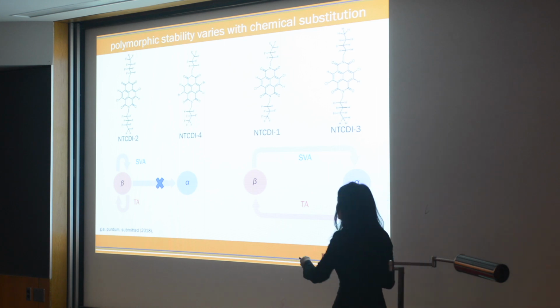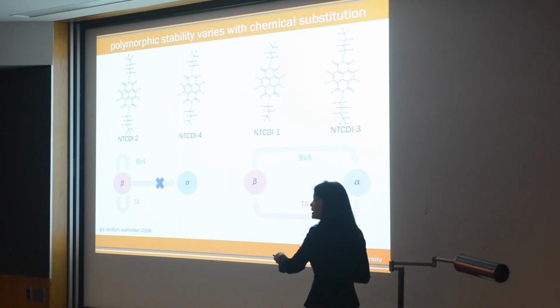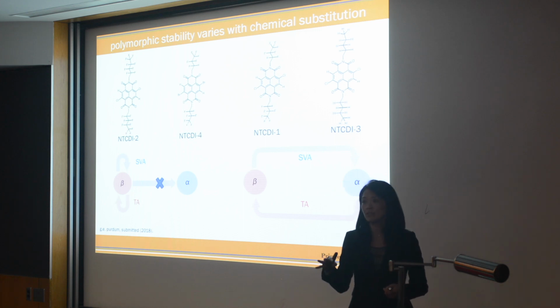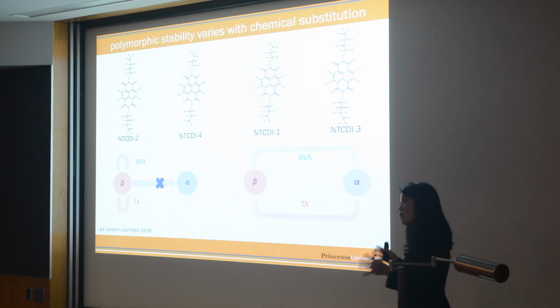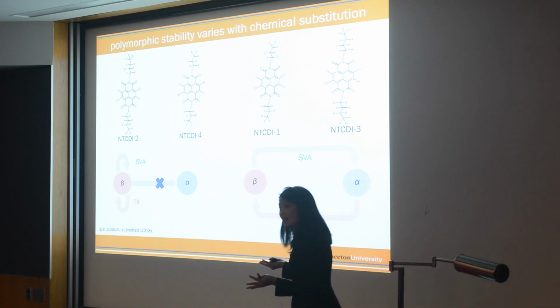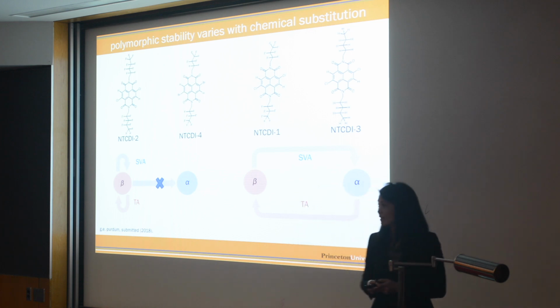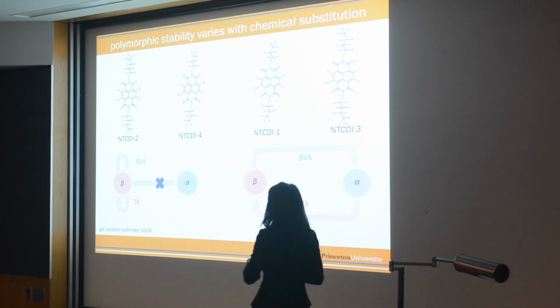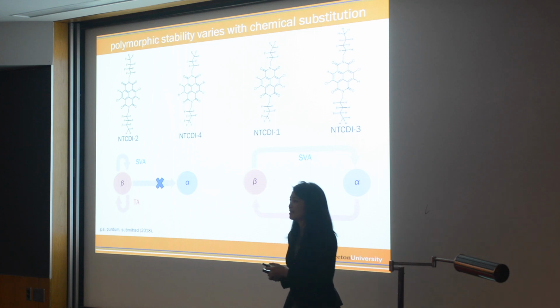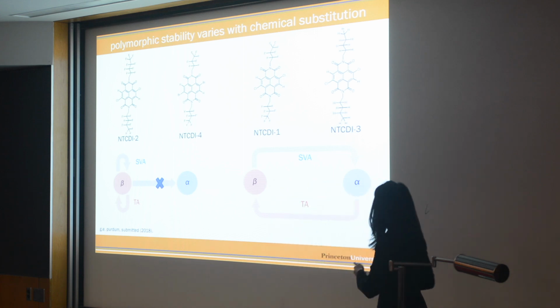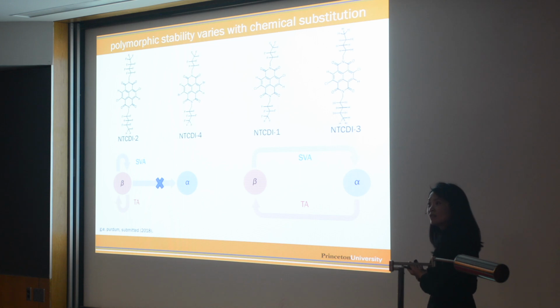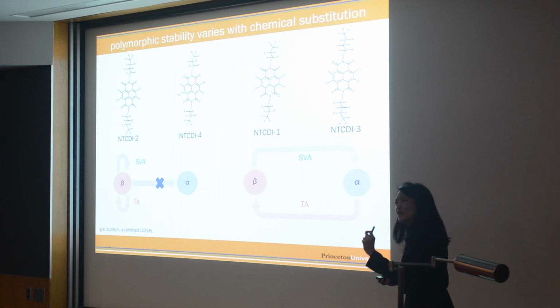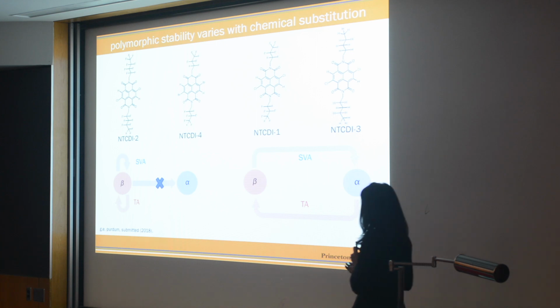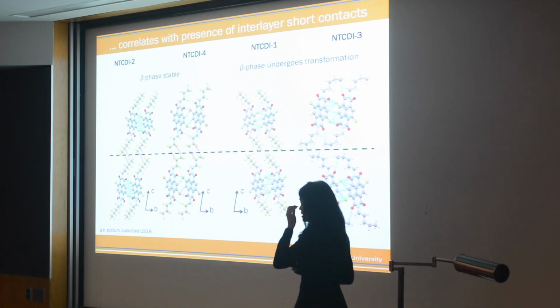Now, curiously, with NT-CDI2 and NT-CDI4, you access the beta phase, and then no matter what you do, you're stuck in the beta phase. We know an alpha phase exists because we can grow single crystals of the alpha phase. And yet, in thin films, we can't seem to access the alpha phase. So there are big differences in thin films that we're not seeing in single crystals. The question is, why is this the case? Why can't we access the alpha phase with NT-CDI2 and 4, but we can go back and forth in NT-CDI1 and 3? And remember, the chemical differences are very, very small in these systems. So we searched for a long, long time, and these are the correlations that we found.